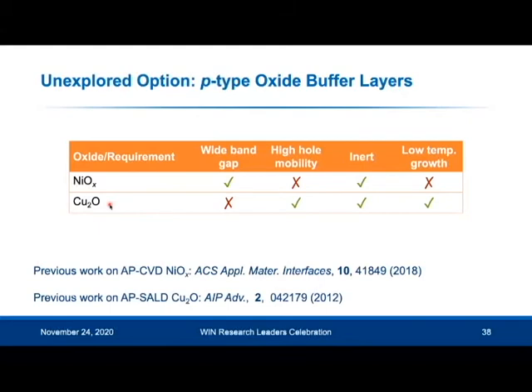And of these two, we picked Cu2O because this can be grown at relatively low temperatures. So there's a previous work by David Muñoz-Rojas, who previously also worked in Cambridge, who now has his own group in France. And he showed that we can grow Cu2O using APSALD at temperatures of only 125 degrees Celsius. By contrast, we found that we need to use deposition temperatures of 300 degrees Celsius or higher to grow the nickel oxide. And that, of course, is too high to grow oxides onto perovskites.